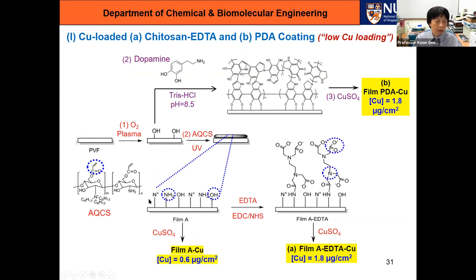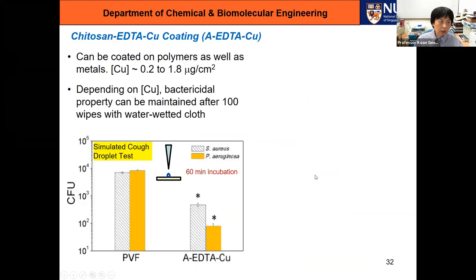And then we use the groups of this quaternized chitosan to react with EDTA. And then we have additional functional groups that we can increase the copper interaction. So you can see that we can increase copper interaction by using EDTA on top of the quaternized chitosan. So let me just show the results for one of them, which is the chitosan EDTA copper coating.